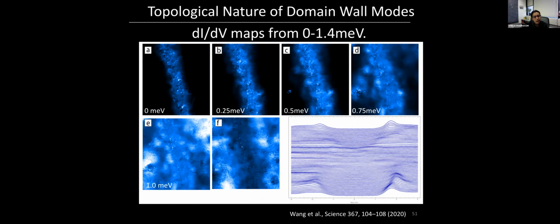And then you can do other checks. This is just one example of a check. You can take density of states maps as a function of energy. Right at 0 bias, this is the domain wall. You can see that at 0 bias, you have a nicely confined state living exactly in the region of the domain wall. As you increase energy, the width of the state, the spatial extent, actually increases. And by the time you get to 1 millivolt, it basically fills up the entire field of view.